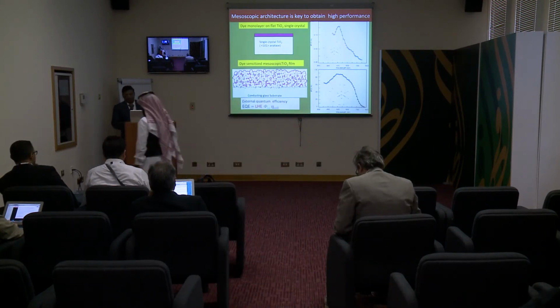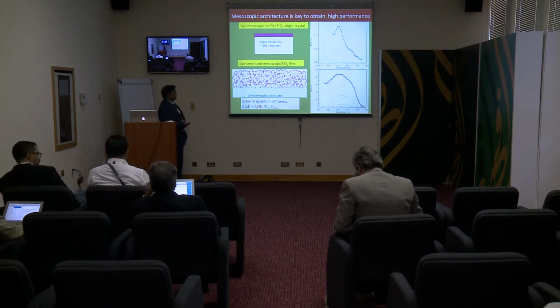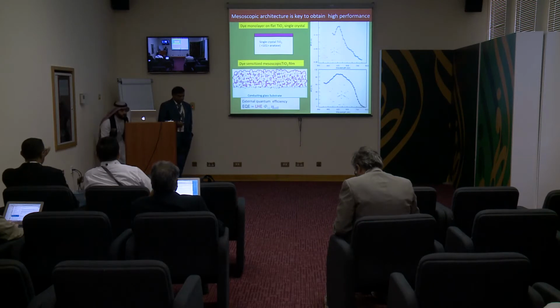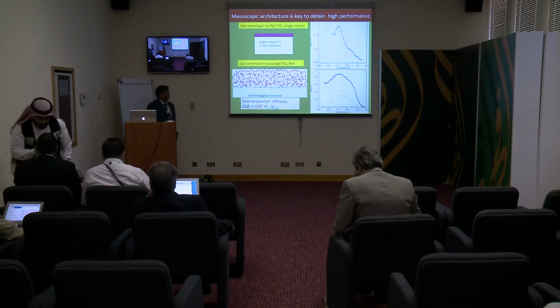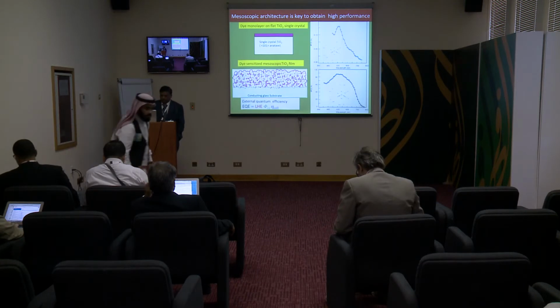If you look at the dye-sensitized solar cell, the breakthrough came from applying the mesoscopic TiO2 film. If you use a single crystal TiO2, the IPCE is 0.13% efficiency, whereas with the mesoporous structure, the IPCE is more than 80%, which shows the advantages of mesoporous TiO2 film as a substrate for dye-sensitized solar cells. The main reason for this advantage is the surface area increasing by 10,000 fold compared to the single crystal.